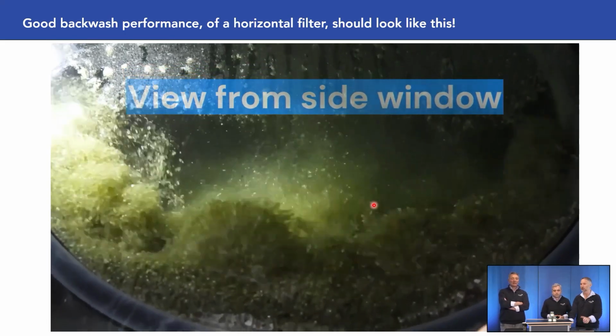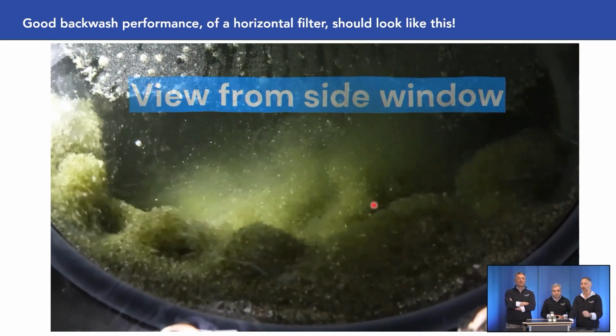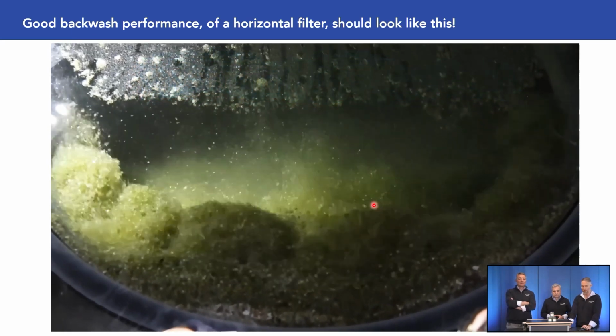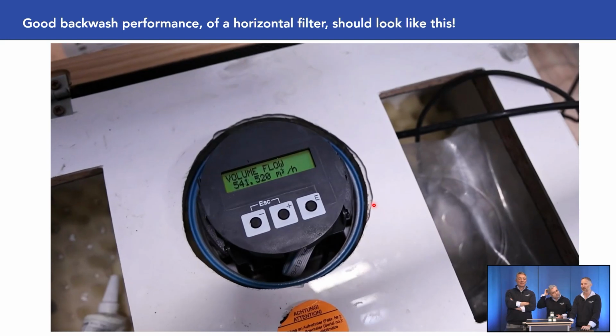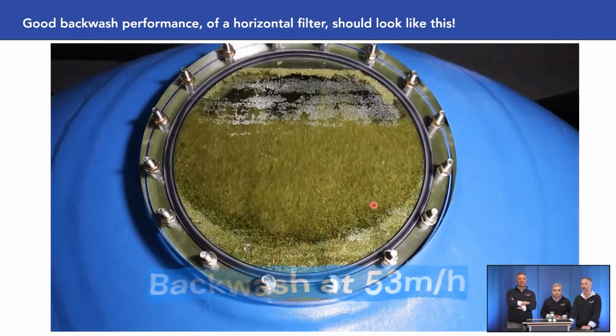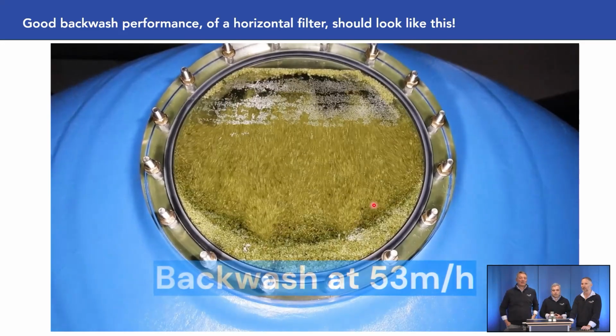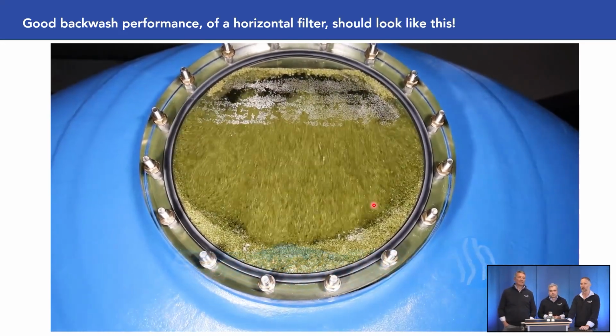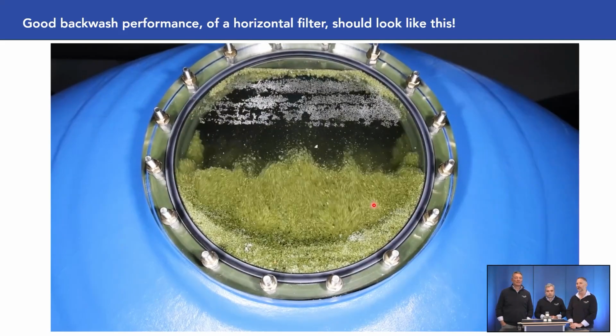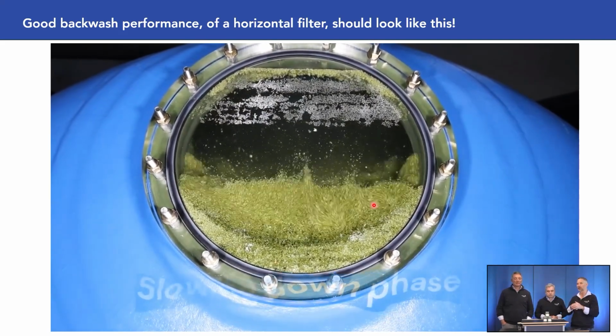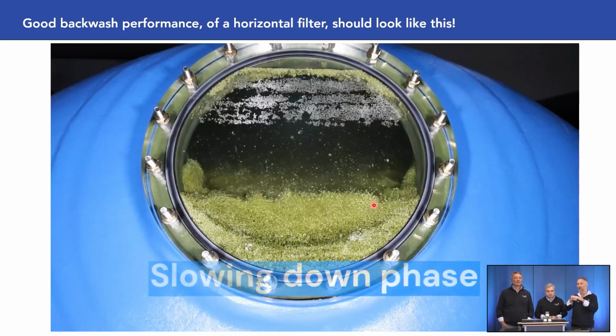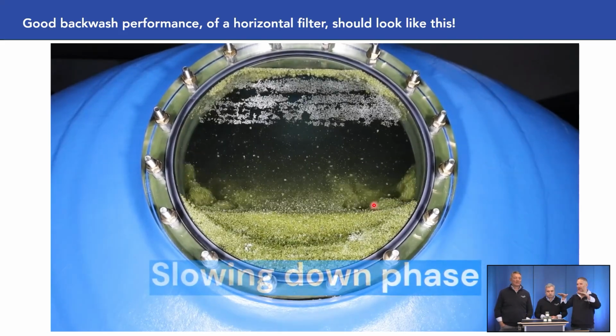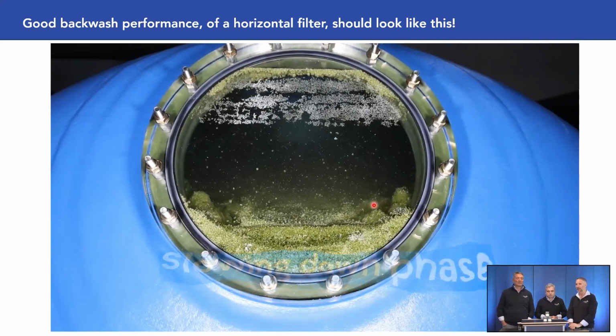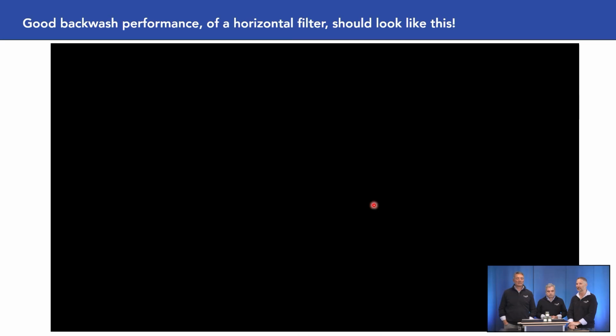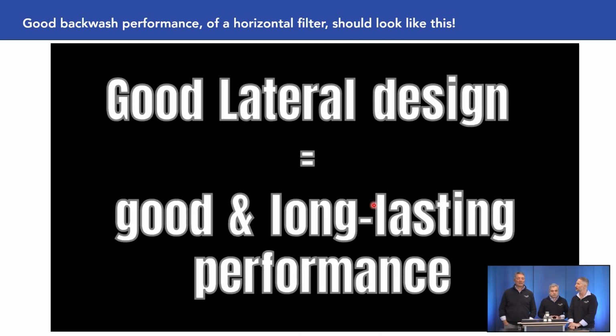And then also to test, because sometimes we do heavy metal removals, and then we definitely want greater than 50 meters per hour, we also did a backwash at 53 meters per hour. And look at that great fluidization. Perfect. No loss of media, which meant that it wasn't just boiling in the center of the filter. And then during the slowdown phase, you can see where we were slowing down the velocities. You can see very evenly how the bed was dropping down into place, ending off with a perfectly level bed again throughout the whole filter. Well, you have done it, K2. Yes. Congratulations.